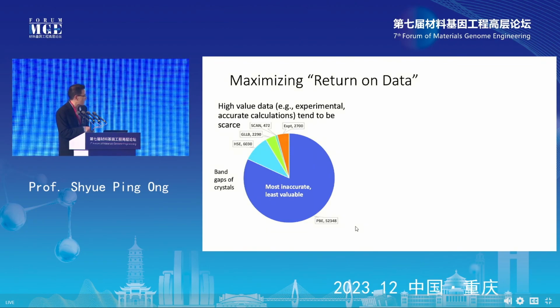So for instance, we can actually get the band gap of crystals using what is called a PBE functional in DFT calculations. And this is very cheap, right? We can do this for a lot of materials. And just going to the Materials Project, you can get about 52,000 band gaps for different crystals, right? Now, we can of course also do more expensive calculations, so things like using a hybrid functional like the HSE functional. And these band gaps are a lot more accurate, but they are also a lot more expensive to calculate, right? So the data set size for something like a HSE functional is about 6,000. So almost one order of magnitude smaller, right?